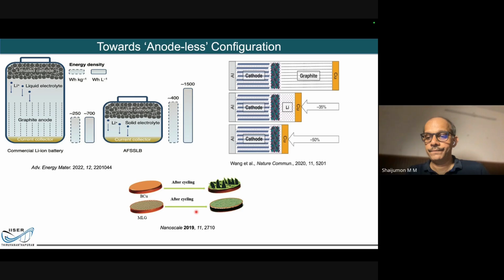Issues are still there because if I take a simple copper, and the surface is not great, after several cycles dendrites will penetrate. So it is important to engineer the surface by putting some very thin coating onto it, making it smooth, so that there are no compatibility issues with the lithium. Lithium nicely comes and gets deposited onto it without forming dendrites. So that's what is called an anodeless configuration.